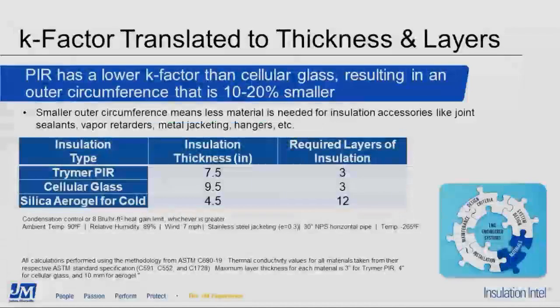Let's consider how the K factors, or lambda, that is the thermal conductivity, of several LNG insulation materials translate into the total thickness required and the number of layers required. As mentioned on the previous slide, the superior, that is lower, thermal conductivity of PIR compared to cell glass translates directly into a lower thickness being used, but this thickness reduction is only part of the story. Using PIR insulation also yields an overall outer insulation circumference that is 10 to 20% smaller than that of cell glass. This smaller outer circumference means less material is used for joint sealants, vapor retarders, metal jacketing, etc.